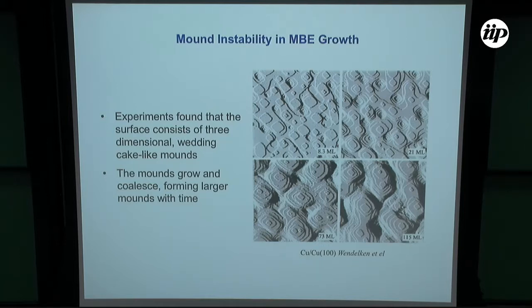And you can see in this picture beautifully that the system evolves into these little hills that grow. This is 8 layers. This is 21 layers. This is 73 layers, 115 layers. So what's happening is that you have terraces, islands that run into each other. They grow, and they grow, and they grow as you deposit more and more atoms. So the main question, of course, is what is this? Where does this instability come from, to the formation of these mounds?